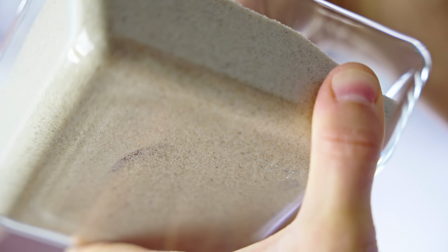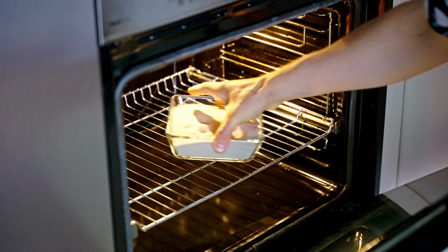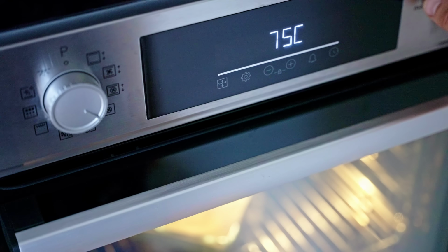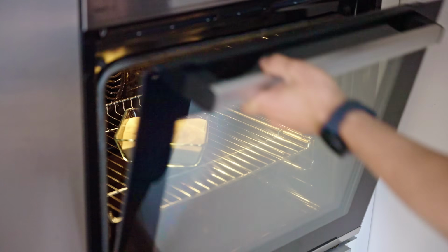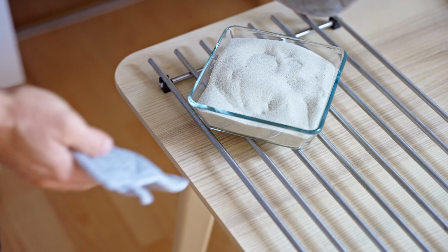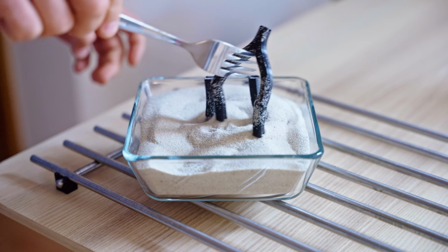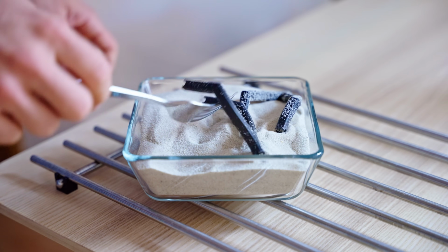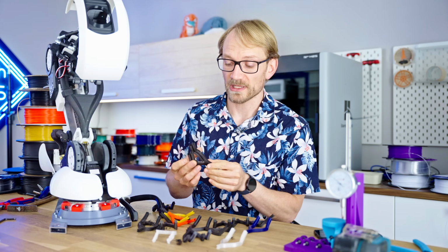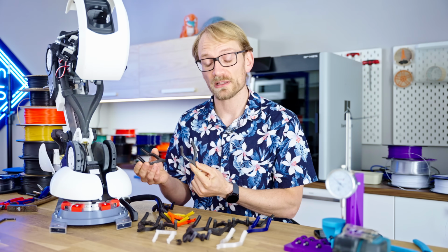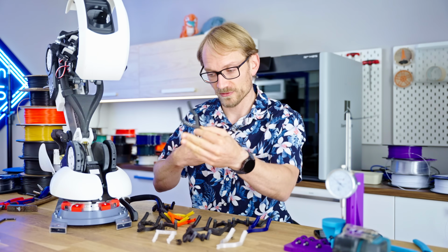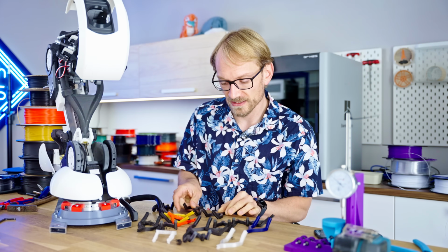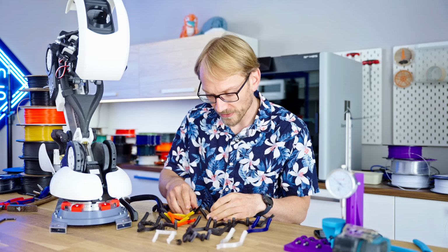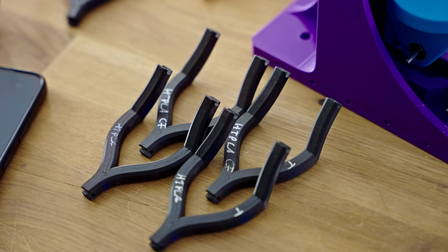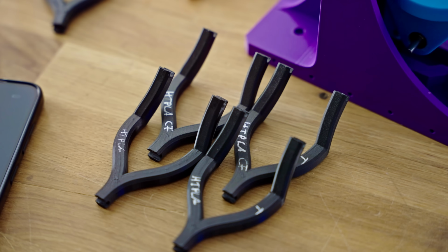You will find heat treat recommendations ranging from 60 degrees for 12 hours to 130 degrees for 10 minutes. I'm choosing the middle ground here, and I'm hoping this will keep warping in check while also giving me most of the benefits of the improved rigidity and strength. One of the things that typically happens when you heat treat HTPLA is that it shrinks in the XY direction and slightly grows in the Z direction. But I think the sand method actually worked pretty well, and keeping the temperatures low also seemed to help.